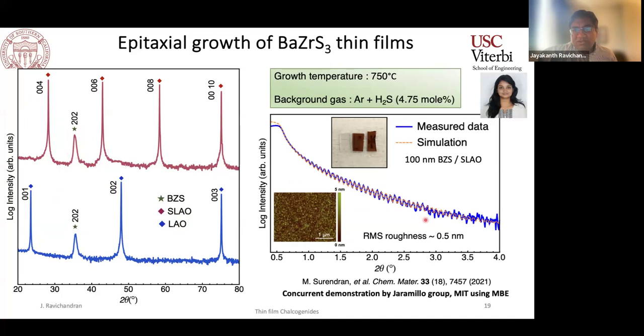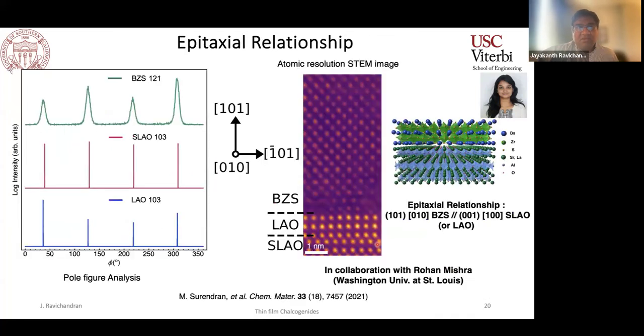When you do X-ray reflectivity, you get reasonably smooth films. You may want to remember that the substrates are not necessarily ideally lattice matched or chemically very compatible systems. But we were pretty happy that we were able to achieve this back in 2021. And this was a concurrent demonstration of chalcogenide BaZrS3 thin film growth with Professor Rafael Jaramillo's group at MIT, and they had used MBE to grow these materials.